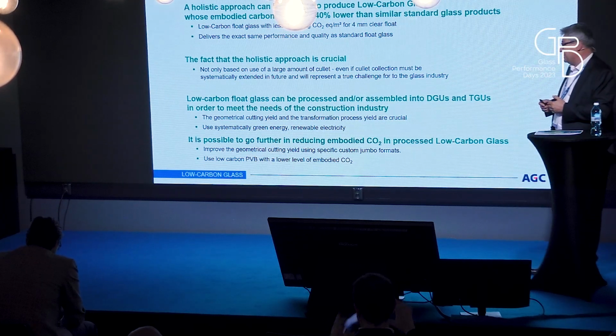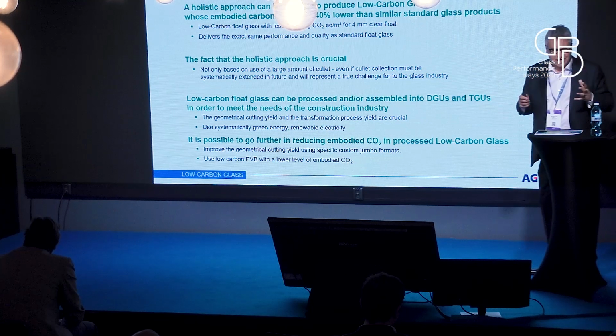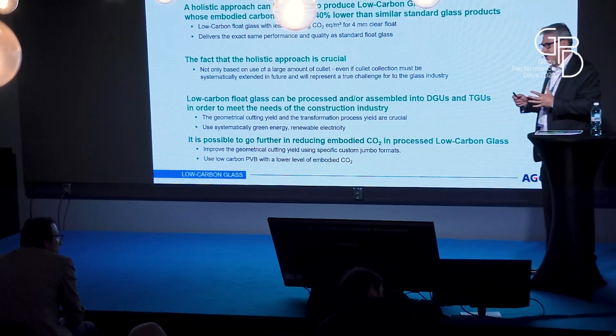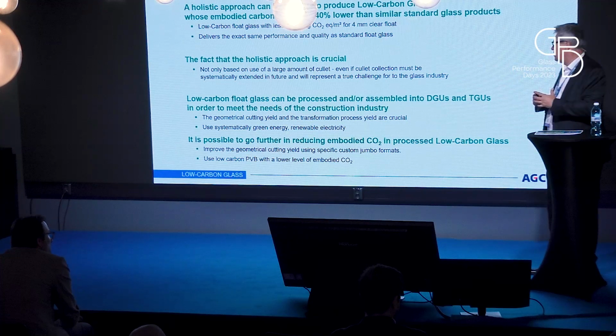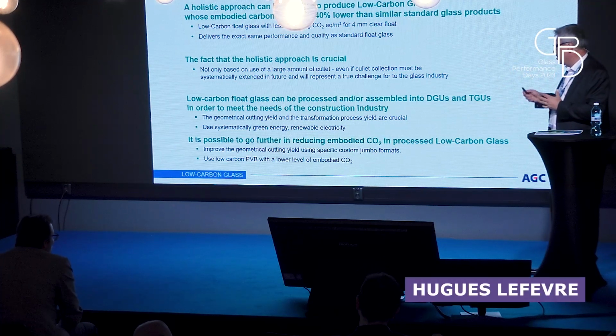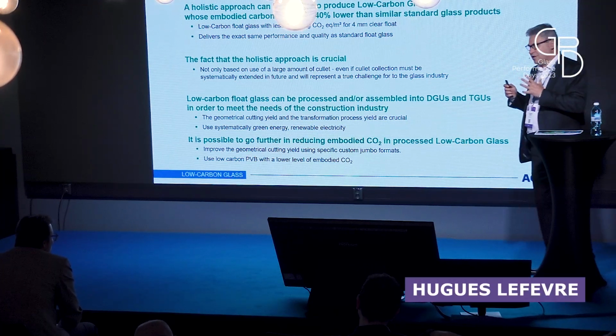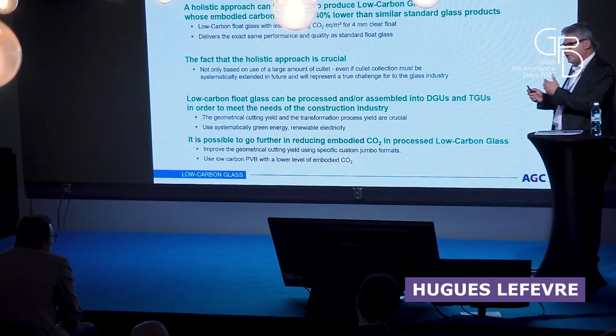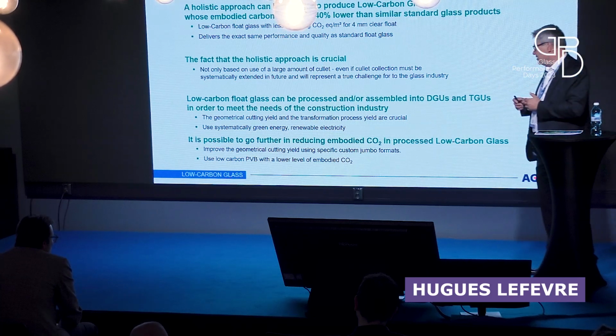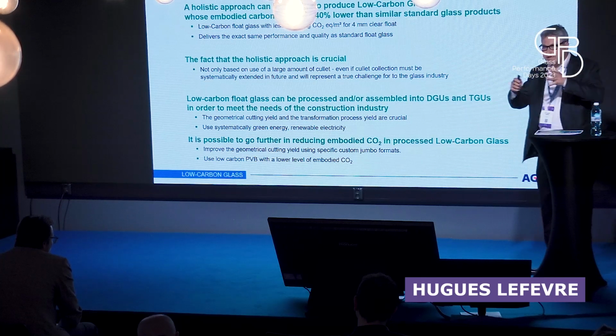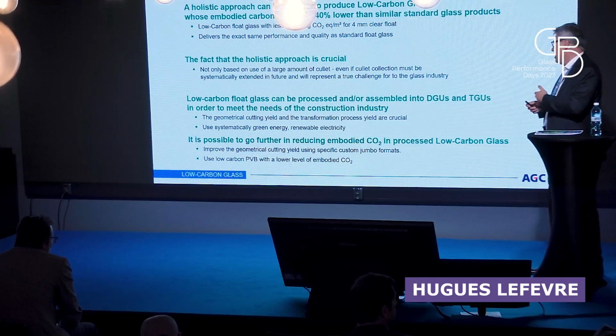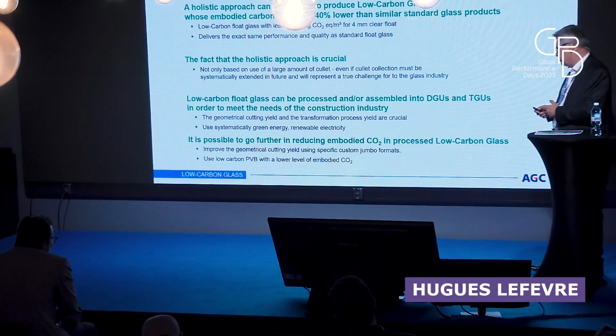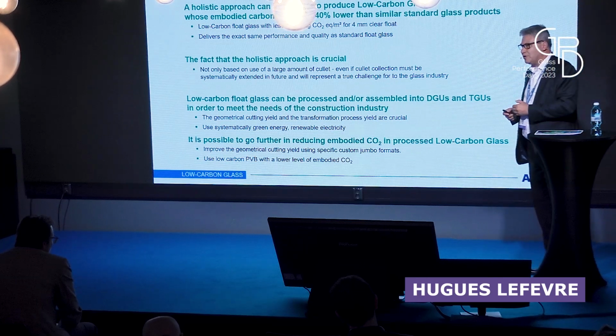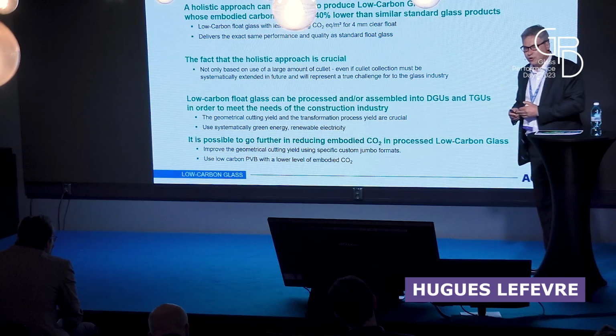So, to conclude, I have shown it is really possible to decrease by 40% at least the float production. The fact that a holistic approach is for us very important, not focusing only on the cullet. There is a really holistic approach. Low carbon transform glass is also important, especially for double, triple glazing, laminated, and so on. And it's possible to go further by improving the cutting yields, and we can think of jumbos with different dimensions or things like this. And also at the level of laminated, to go deeper about the low carbon interlayer.